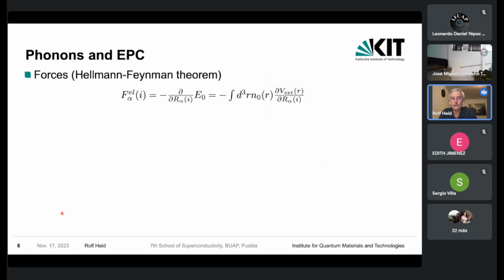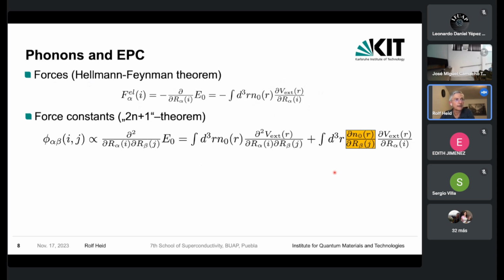And now one can carry that further on to the derivatives of the total energy. One example of such a derivative is given by the forces, which are the first-order derivative of the total energy. And there's the famous Hellmann-Feynman theorem, which in the context of density functional theory states that this quantity can be obtained by calculating just the ground state density, and one has to know the derivative of the external potential only. Only in higher order derivatives does the first-order change in the density enter. Therefore the first-order or linear response of the density is sufficient to calculate second-order derivatives of the total energy, and therefore one can access these force constants by this kind of linear response calculation.